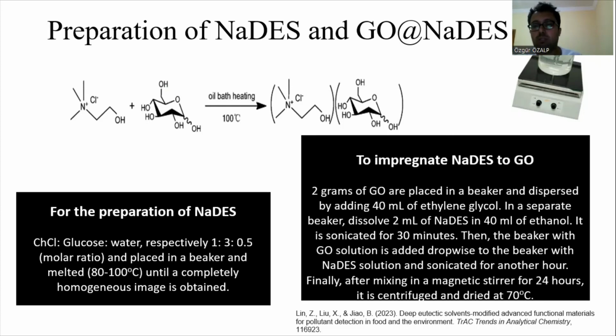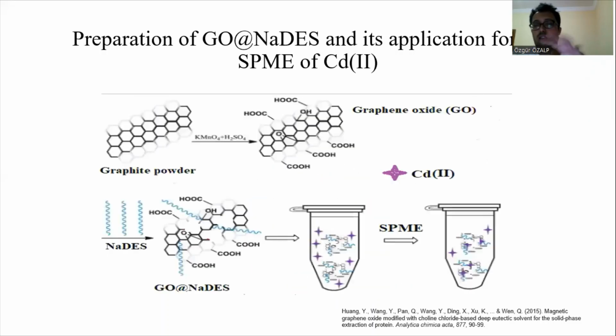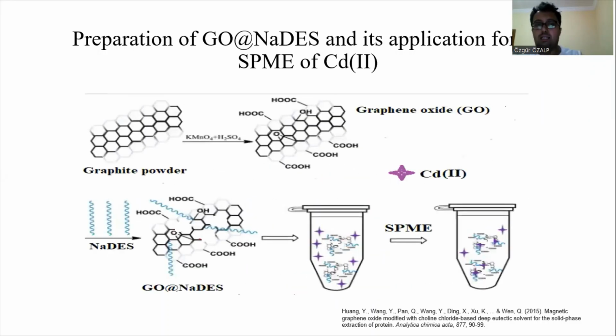After 30 minutes of stirring, the graphene oxide surface is impregnated with natural deep eutectic solvents, and after centrifuging you can see the result. Graphite powder with Hummers' method gives graphene oxide. After the natural deep eutectic solvent is added on the graphene oxide surface, the modified material is used by adding cadmium and buffers, and cadmium extraction is very good.